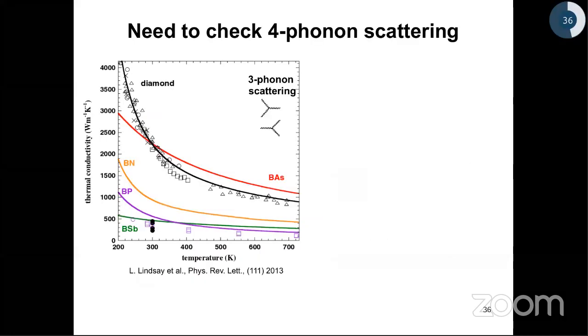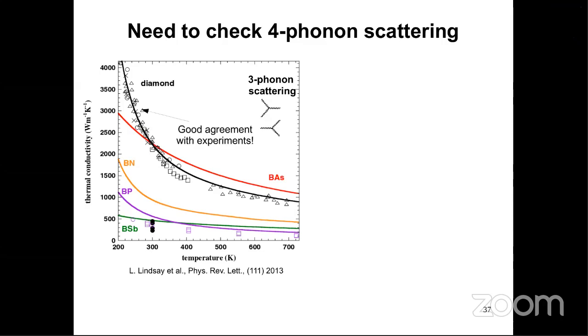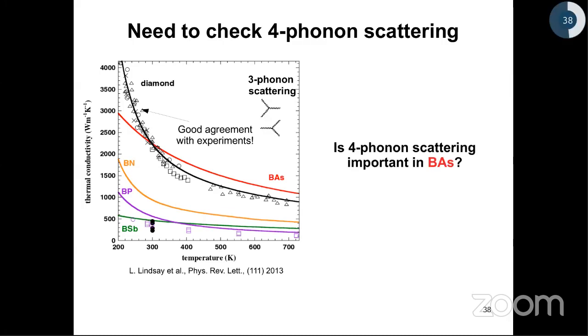In fact, if you go back to the picture I showed you earlier, for the case of diamond, with just 3-phonon scattering calculations, they were able to achieve excellent quantitative agreement with the experimental data. So what this indicates is, in the case of diamond, the 3-phonon scattering picture sufficiently describes thermal transport, and any addition of higher order scattering processes should not change this curve significantly. But the problem is with boron arsenide, it was not available in nature at that time. So they could not conclude whether the 4-phonon scattering processes are weak enough in boron arsenide or not. So the fundamental question that I wanted to address is to quantitatively calculate the effect of 4-phonon scattering on the thermal conductivity of boron arsenide.